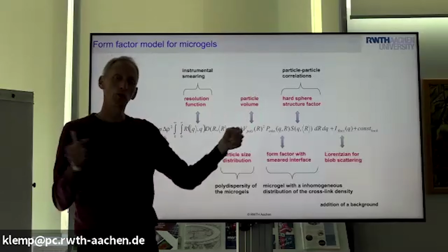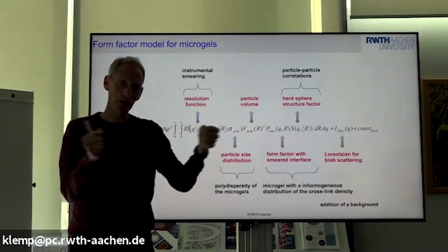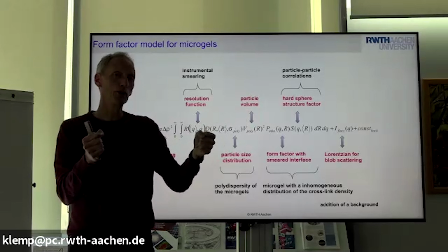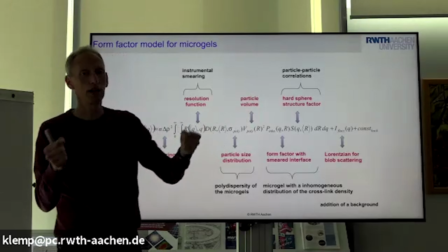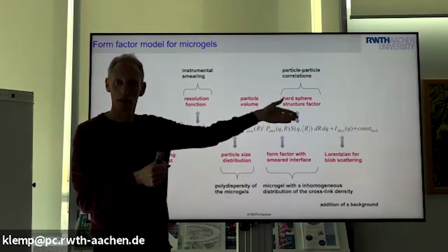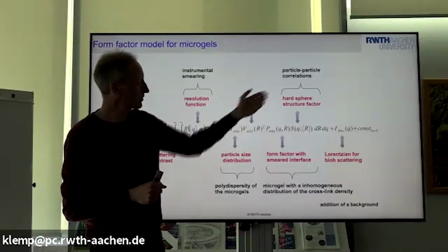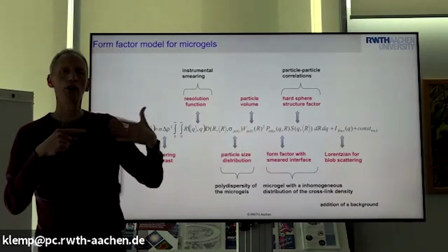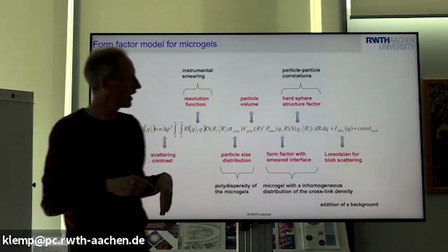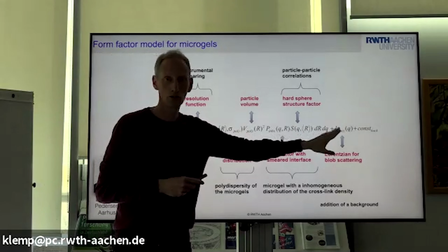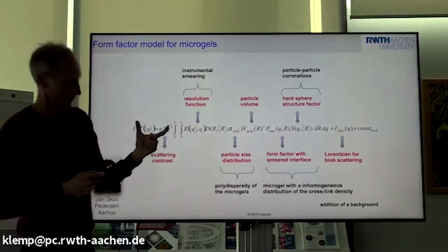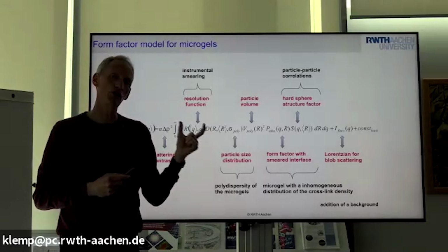The structure factor would give us the interaction between the particles or the microgels. If we go to infinite dilution or to very high dilution, we can neglect the structure factor. Or if we go to higher concentration, we can probe the structure factor. And then when we go to very high scattering angle, to very high Q, we can also look into the internal structure of the microgels at very short length scales.